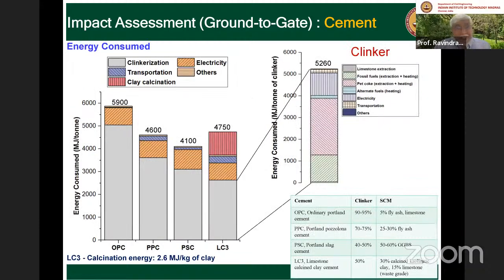I had already mentioned energy is also cost. Energy is use of raw materials. And we see this significant reduction as we go to blended cements, from OPC being about 6,000 megajoules per ton of cement, being the embodied energy, the energy required to produce this. And as we go to lower and lower clinker, it decreases.